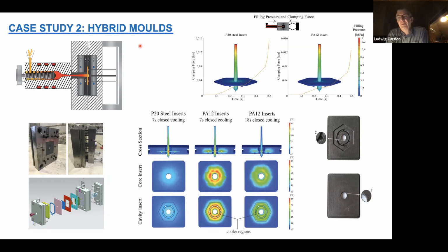There are some possible techniques we discussed with the company. Probably we can try to put a kind of flexible coating on top of the flexible mold. One thing you never may do, that we noticed from the research: when you put a hard coating on the soft polypropylene, on the soft polyamide insert, after 1 or 2 injections, it cracks like the eggshell effect. So that's something you can't do.